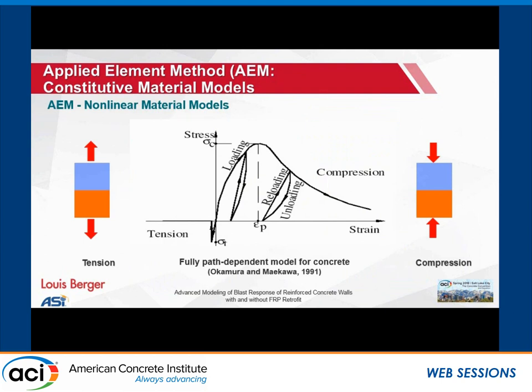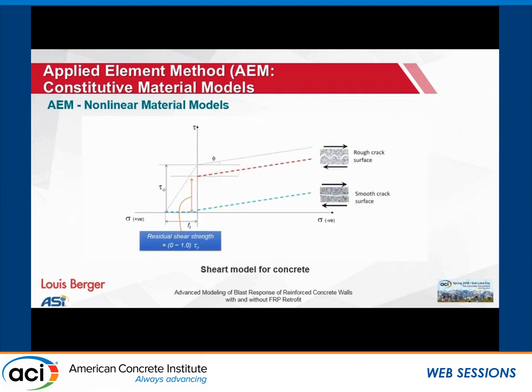The material model in AEM is identical to FEM — you can use the same or similar models for brittle materials. For the concrete model used in this research, modeling differs in tension versus compression. Shear failure is also modeled: if shear stress exceeds shear strength, the springs fail, also considering whether the spring is in tension or compression. Springs in compression have additional shear resistance; springs in tension have significantly reduced shear strength up to cracking, after which there is no shear strength.